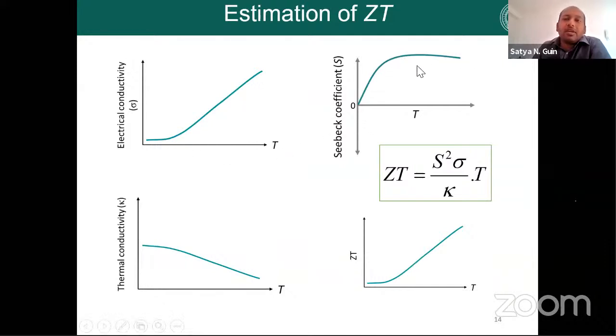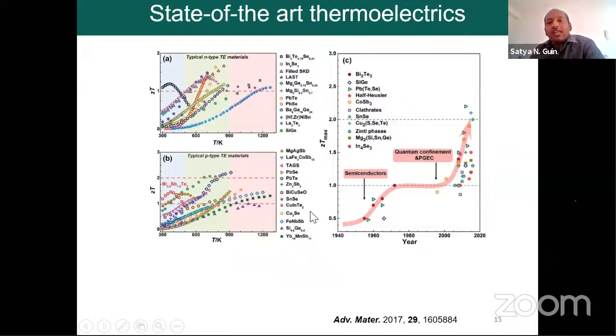And this is how the Seebeck coefficient curve looks after measurement, and this is the thermal conductivity. So you generally measure the electrical conductivity, Seebeck coefficient, and thermal conductivity, and from there we can estimate the overall thermoelectric figure of merit, and this is how the overall curve can look, the thermoelectric figure of merit from all the physical properties measured data. So this is the state-of-the-art thermoelectric in the literature.